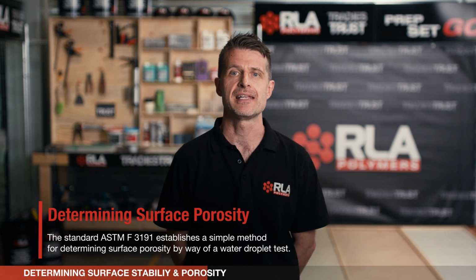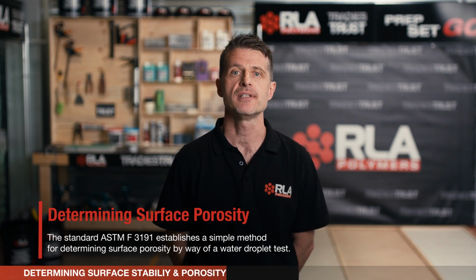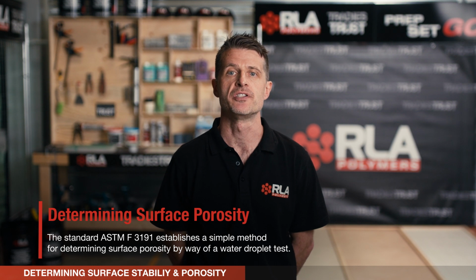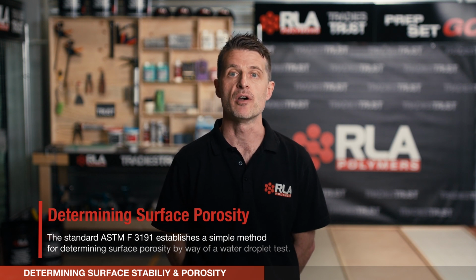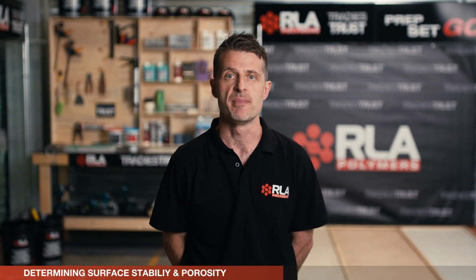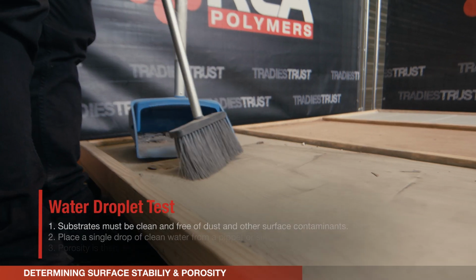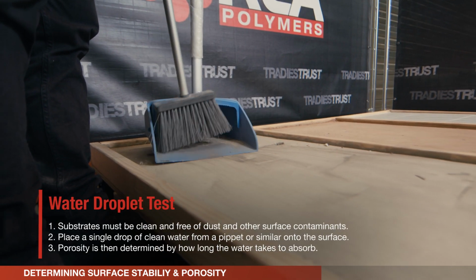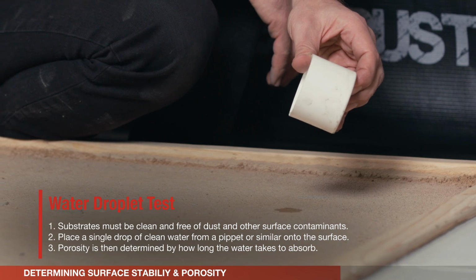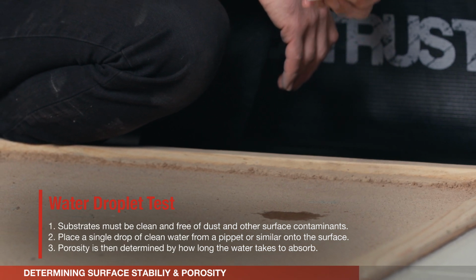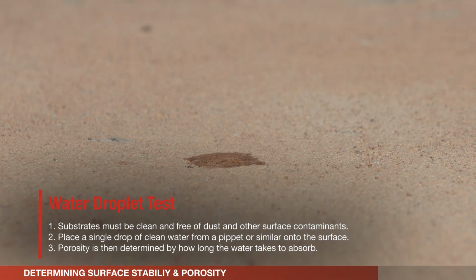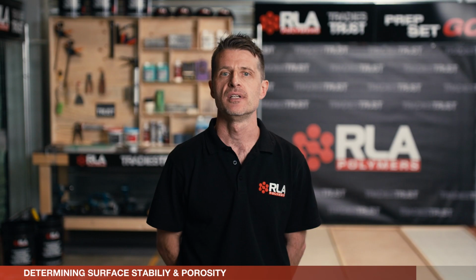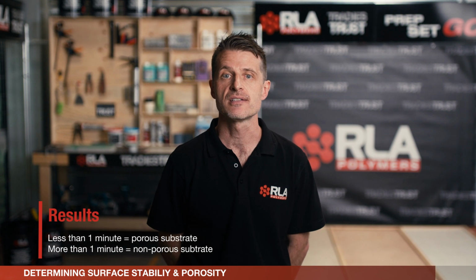So the obvious question: how do you determine the porosity of a surface? The standard ASTM F3191 establishes a simple method for determining surface porosity by way of a water droplet test. The method is as follows. Substrates must be clean and free of dust and other surface contaminants. Place a single drop of clean water onto the surface. The porosity of the substrate is then determined by how long the water takes to absorb into the substrate. According to the standard's guidelines, less than 1 minute is a porous substrate, and more than 1 minute is a non-porous substrate.